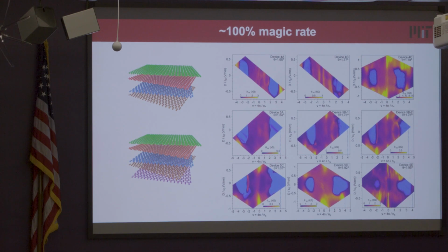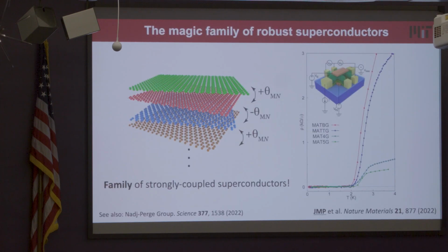On the previous slide, should I be reading into the fact that the high temperature resistivity is dropping so dramatically here? Anything interesting, or is that very easily explained? Oh yeah, that's a good point, and it's related to what he just mentioned. There are other bands present in the background. So basically you're sort of shorting. You're never really in the full band gap. Those Dirac bands and other twisted bilayer graphene-like bands in the larger layer number structures are always present. So you can always conduct through those channels, even if your flat band itself is gapped. Yeah. Okay.